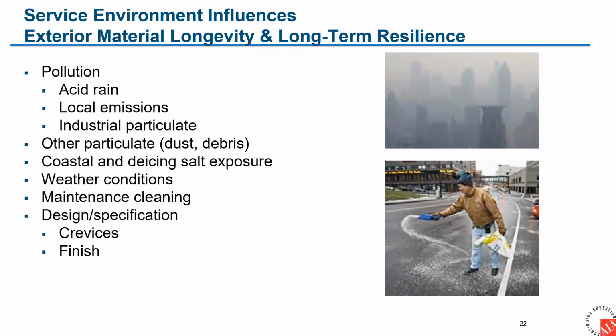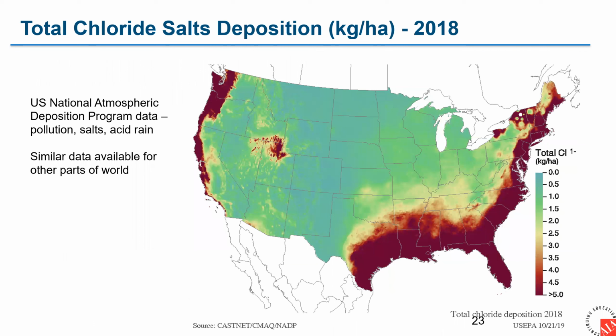There are a variety of things that have to be considered as you're looking at the longevity of materials: pollution, salt exposure, weather conditions, maintenance, and aspects of design that can also facilitate accelerated corrosion. This is the US coastal deposition map. 60% of the US population, 60% of the global population live in a coastal zone. As you can see, the darker kind of burnt orange color is indicative of areas that have significant chloride deposition. There are misconceptions that salts are only present a short distance from the coast, and that's simply not the case. There are similar maps for Europe, Oceania, and other countries. So please do look at that if you're working on a project.